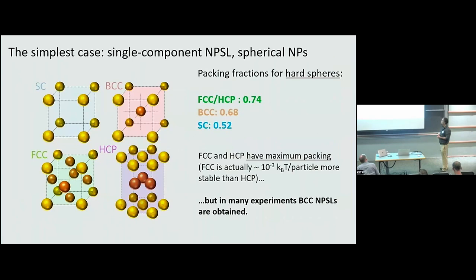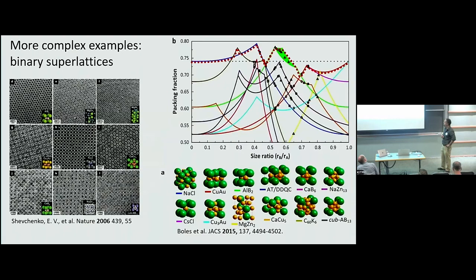I also will address a very simple system in terms of composition, just a single-component nanoparticle superlattice. If you have spherical particles that are hard spheres, then you expect those to pack into the structure with the highest packing fraction, like FCC or HCP. But what happens is that in a lot of experiments with nanoparticles, you get, for example, BCC, so it's a non-close-packed structure, right? And this also happens, of course, in binary superlattices, where you would expect the structure with the highest packing fraction. In this plot, from a paper, you have the packing fraction as a function of the ratio of the sizes of the particles. The structure that will be the most stable one for hard spheres will be just moving over this dashed red line. But then you look at the experiments and you have points all over the place.